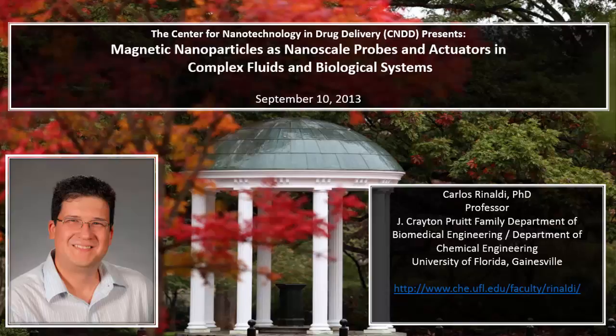So in summary, nanoscale heat delivery appears to be a promising approach to destroy cancer cells, even though heat conduction arguments indicate that there should be no local temperature rise. Experiments with cells and thermoresponsive polymers provide evidence of local thermal effects. And in my opinion, for many reasons, these observations may be due to energy flow in the vicinity of nanoparticles. This paradigm that you have to raise the temperature to hyperthermia range to kill cells may be wrong. Our results demonstrate that you can kill cells without temperature rise.